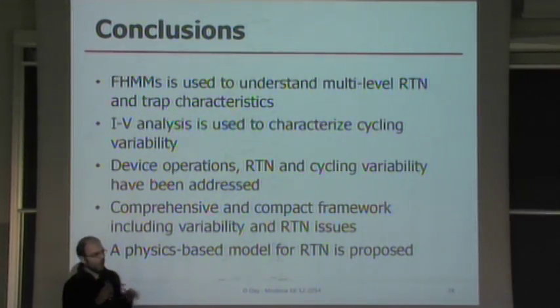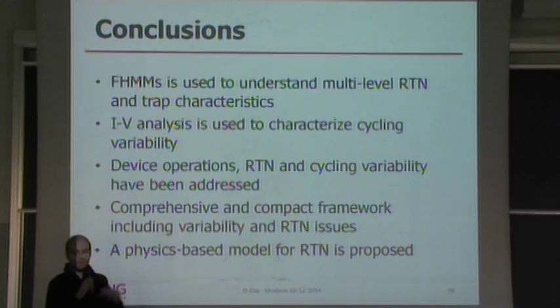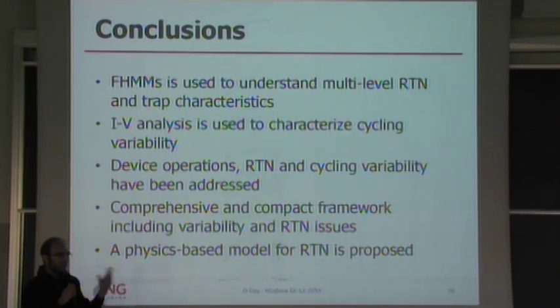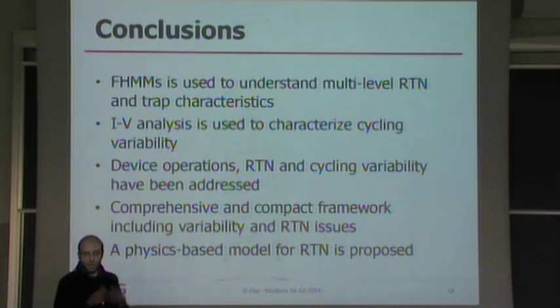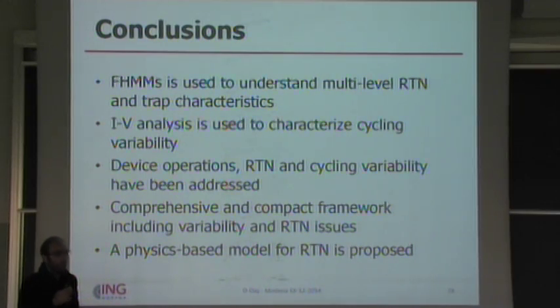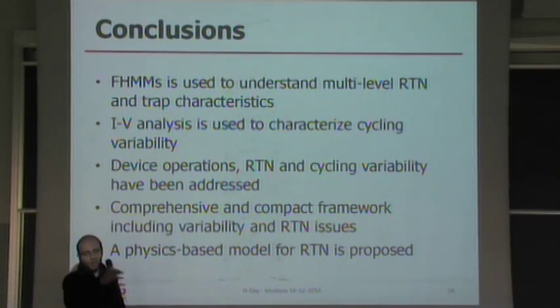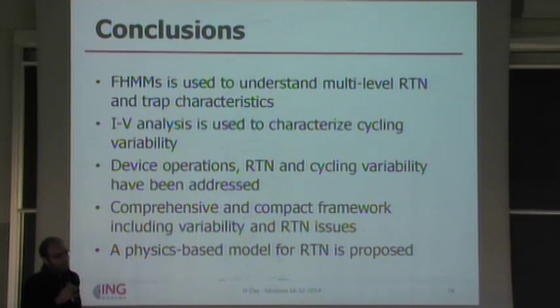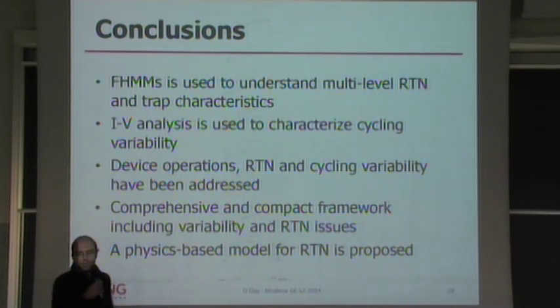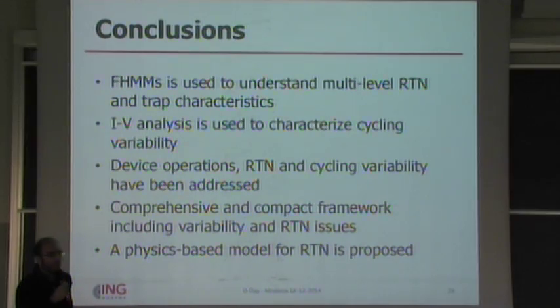So concluding, we successfully analyzed the behavior of the trap. We developed a compact model which is able to capture the statistic and the dynamic characteristics, and also the cycling variability. Thanks to the IV compact model and the model we developed to analyze RTN, combined together, we ended up with a possible explanation for this complex phenomenon in these devices, and incorporated the whole thing in a unified framework. And I also have to thank, last but not least, Sematech for giving us samples and for a fruitful collaboration throughout all these 3 years. So thank you so much.